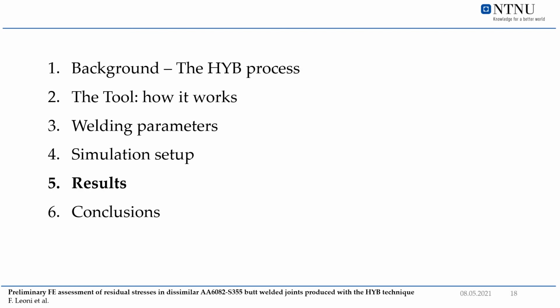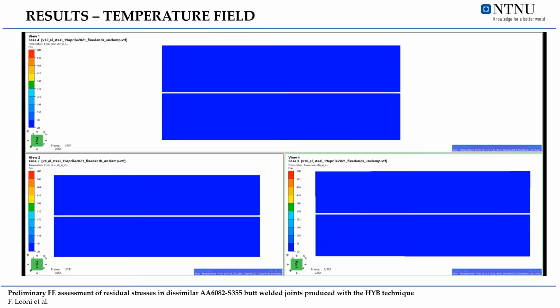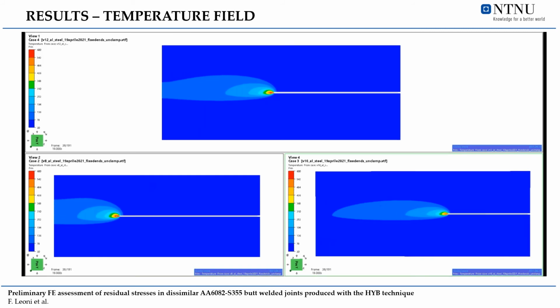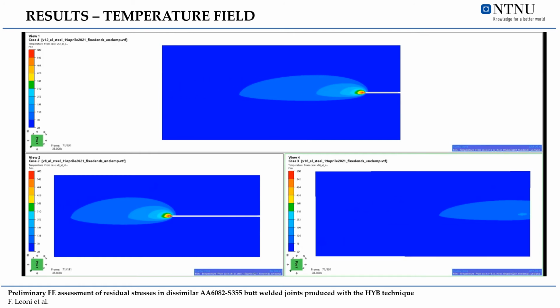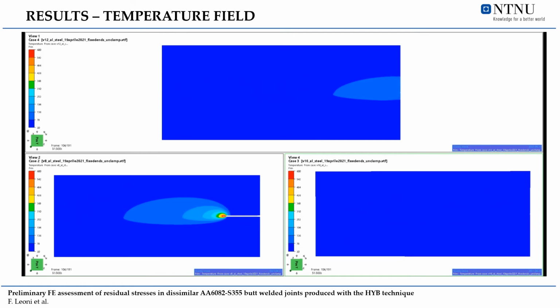Let's now see the results obtained. The thermal history is plotted for 3 welding speeds. At the top there is the aluminum, where the heat is transferred much faster than in the steel, which is placed at the bottom. As can be seen, the temperatures are relatively low, and this is in accordance with experiments, where melting of the parent material is not observed. This confirms the validity of the heat generation model employed.